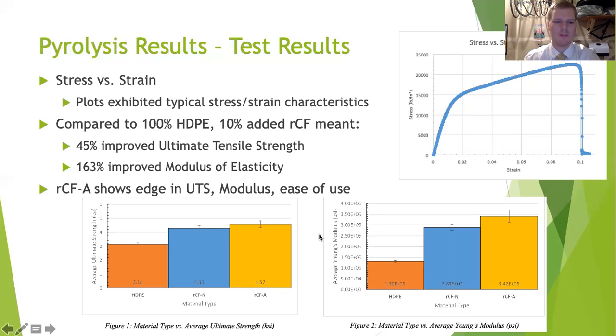This was really significant to me because that showed that with both recycled carbon fibers, you add that to the HDPE, you get better mechanical results, makes sense. But I was interested to see that that ambient recycled carbon fiber did have an edge over the nitrogen sample, the inert one, which is great for mechanical properties, but also for people who want to incorporate this process. It's of course easier and less expensive if you don't have to invest in that nitrogen setup to burn everything off for pyrolysis. So that's pretty nice.